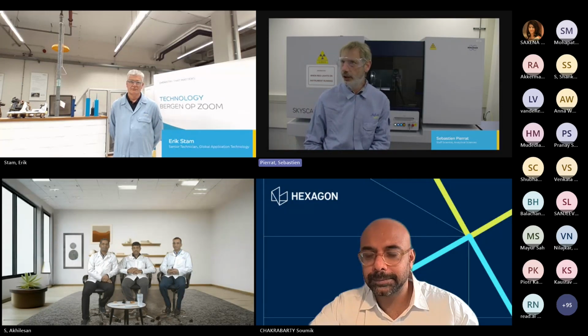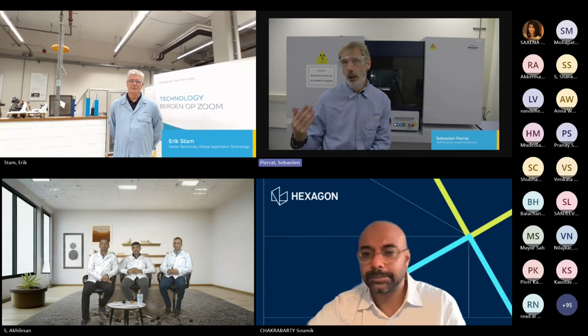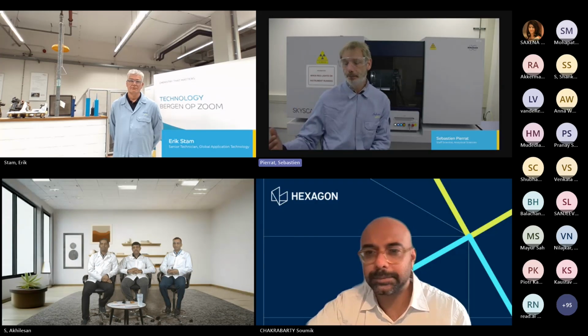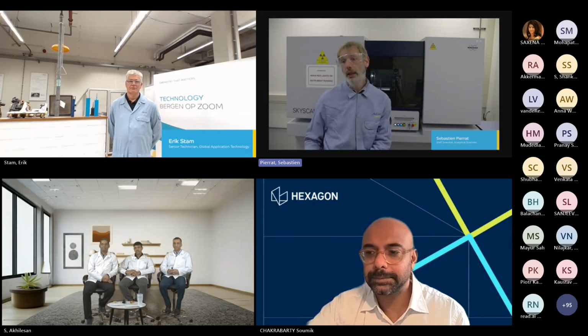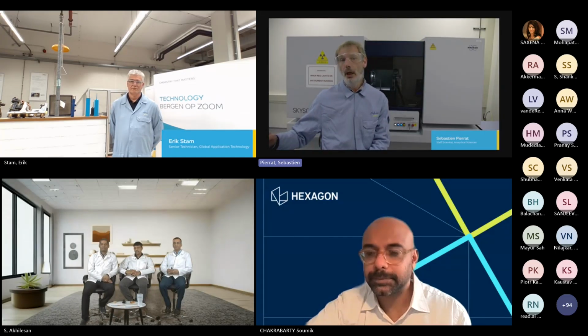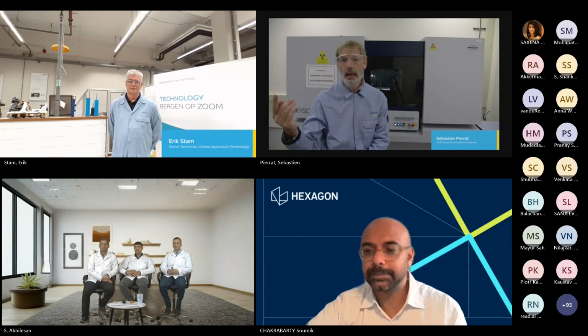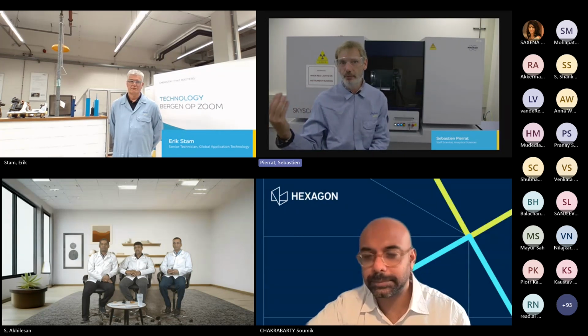The second part of the question was about the parameters which are really important to take into account to have a good scan, right? So the contrast is very important. This we adjust with the X-ray. We then need to optimize the exposure time to have a signal which is strong enough, but so that the camera is not saturated. That's really the two major important parameters. And then we can play as well with different settings like the number of averaged frames and the number of projections that we take to limit the artifacts and to achieve better resolution.